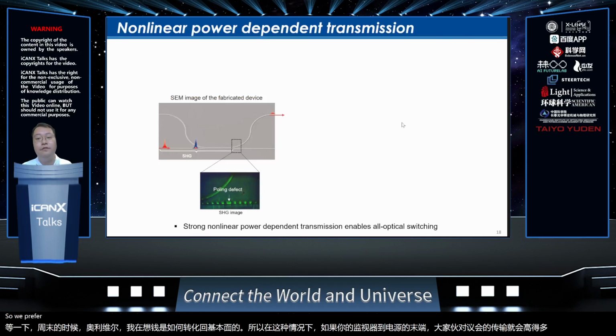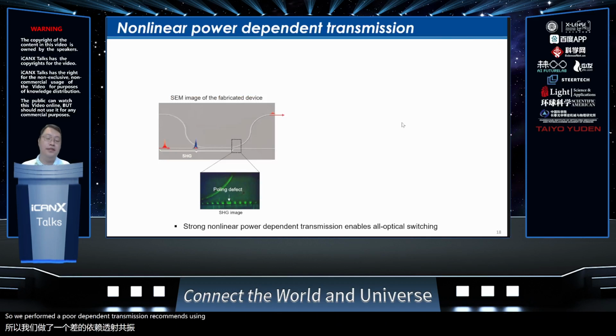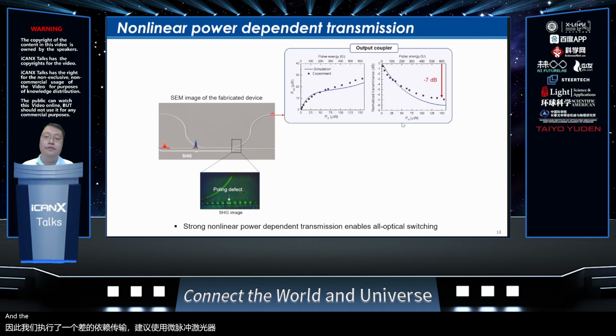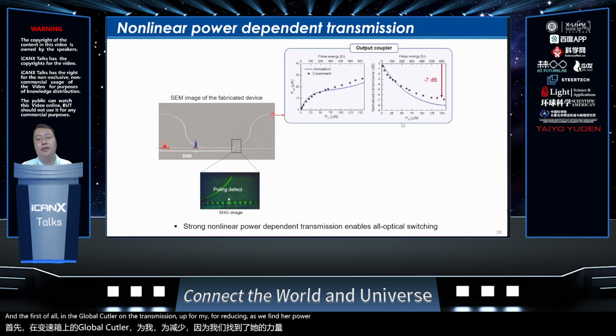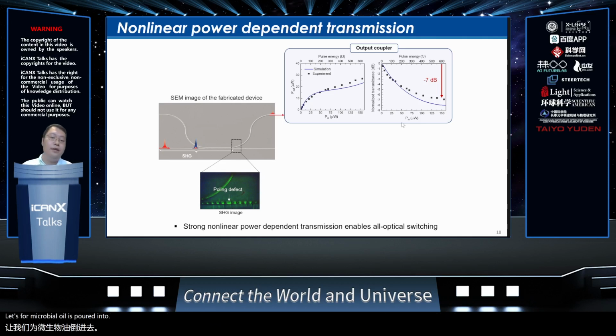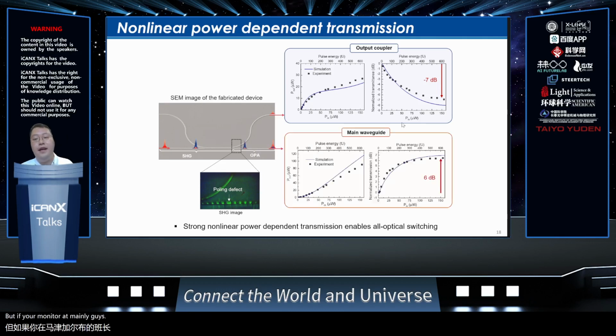So we perform the power-dependent transmission measurement using the 2-micron pulse laser. And first of all, in the output coupler, the transmission of 2 micron reduces as we crank the power, because in the first half, we have second harmonic generation. So the 2 micron is converting to 1 micron and gets strongly depleted. But if you monitor at the main waveguide, we see that 2 micron transmission increases by more than 5 dB, indicating that OPA is working. So the 2 micron is recovered from the second harmonic. So this nonlinear power-dependent transmission makes it possible to use our device to perform optical switching.